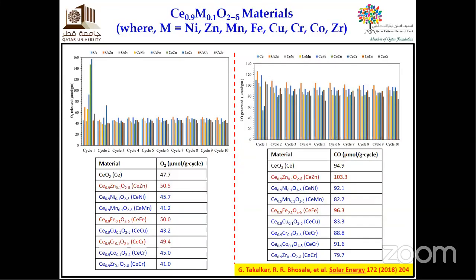The red color means that the dopant actually improves the O2 production capacity or CO production capacity, and blue means it doesn't have much effect. So if you check the first part, which is the O2 production capacity, the thermal reduction capacity, zinc, iron, and chromium actually help to improve the O2 release capacity of ceria, and nickel, manganese, copper, cobalt, and zirconium are not that beneficial. On the other hand, if you go to the CO production capacity, only zinc and iron are capable of helping ceria to produce more CO as compared to pure ceria, and other metal oxides are producing a lower amount of CO. So from this study, we identified that zinc, iron, and chromium are suitable for the next study. So instead of testing all the materials again, we can focus on zinc, iron, and chromium only.